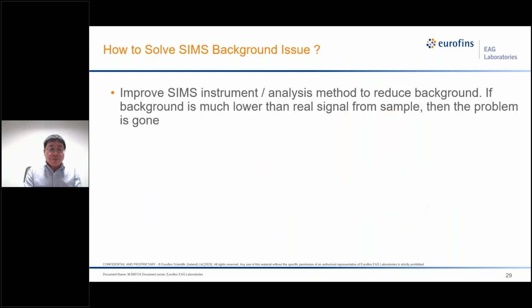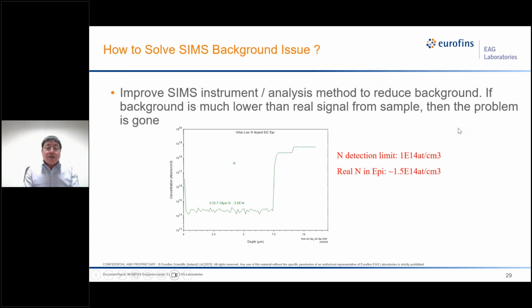So how to solve this background problem? We can improve the SIMS instrument analysis method to reduce background. If background is much lower than the real signal from the sample, then the problem is gone. Here is the depth profile we obtained. The best nitrogen detection limit of 1E14 is achieved. To get such a low background, it takes a lot of effort for us, so I'm not going to go into the details here.